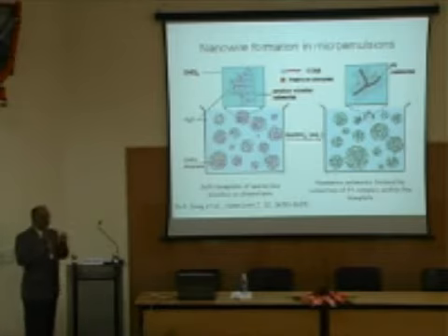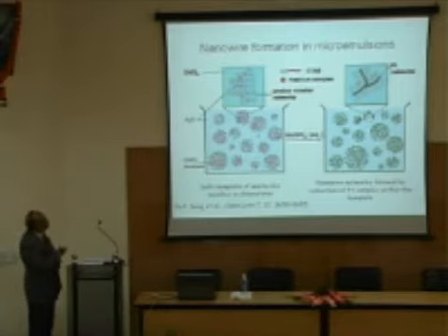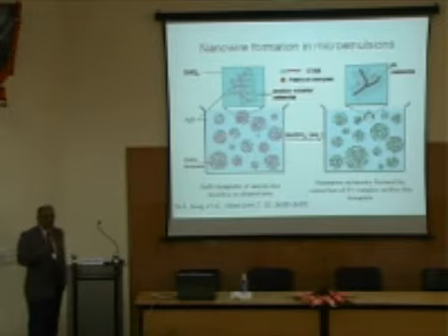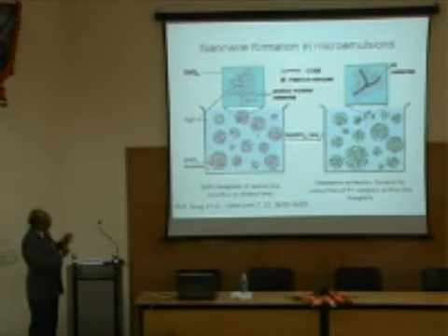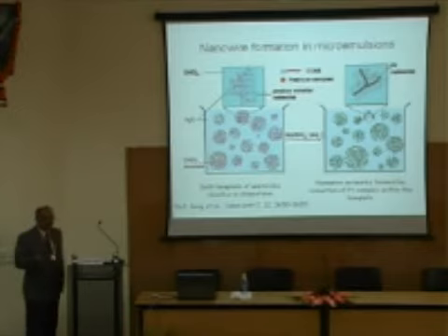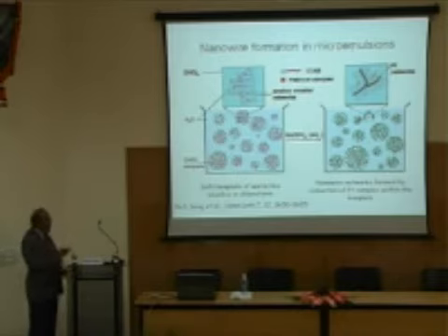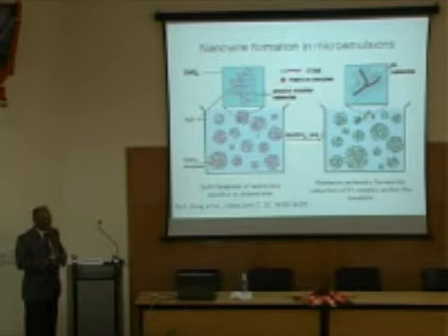lots of different structures. They can be spherical, they can be lamellar, they can be worm-like. These are called worm-like micelles. So it depends on the concentration of different chemicals that you have taken. To make one particular solution of a microemulsion, you need 3-4 components. You may need alcohol, you may need alkane and some water, and the thermodynamics will make the molecules align in a particular fashion because it has to reduce its energy, right.